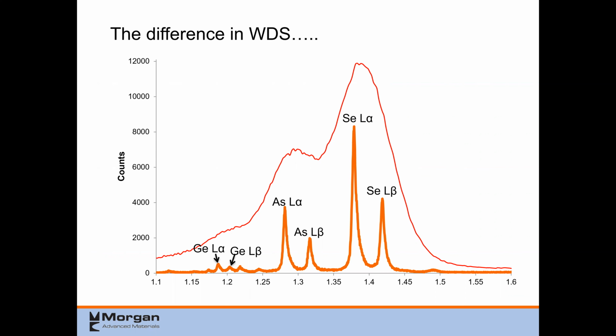And EDS is the red line that you can see, where the peaks are strongly overlapping. But in WDS, the peaks are separated very nicely. So you can very clearly see each peak individually, and you can get an exact stoichiometry for this. So for this project, I was able to do a lot of analysis for them, where I was looking at the ratio of the three elements of interest and telling them very precisely what their composition was.